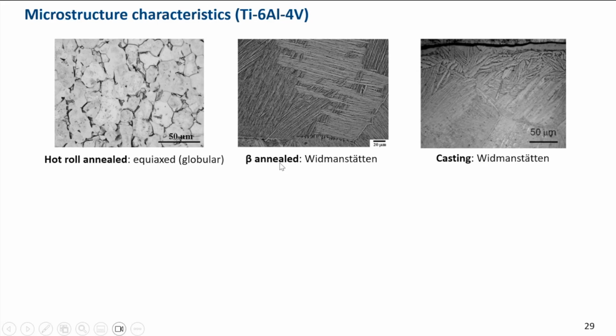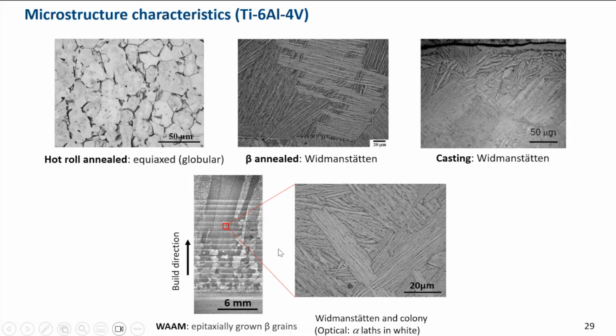But with a beta annealing, you create a Widmanstätten microstructure, and that causes a lot of resistance. It's quite a large colony of alpha laths. So the crack has to grow zigzag around it. It's a lot of resistance. And casting being the best is because they have the similar Widmanstätten microstructure with very large colonies of the alpha laths in the same orientations. For additively manufactured material, if we do a beta annealing, we could achieve this situation like the casting. But if we don't do the post-process annealing, it will be just like the ordinary lamellar structure. So the microstructure really determines how fast the crack propagates.